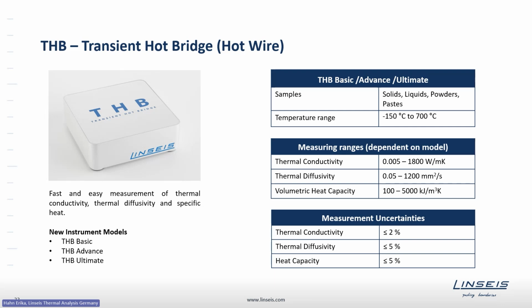Basically, the instrument can measure very low conductive materials, also quite high conductive materials. And you can use this tool for solids, liquids, powders, pastes, so more or less the complete range of materials. The temperature range is going from minus 150 degrees Celsius up to 700 degrees Celsius. The basic unit more or less can measure up to 200 degrees Celsius.